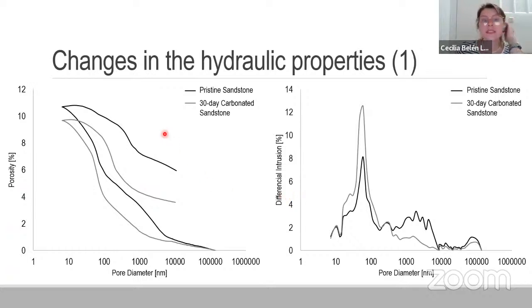In this slide, we can observe that when comparing the porosity of the pristine sample and the porosity of the carbonated sample, there seems to be a reduction in the porosity.